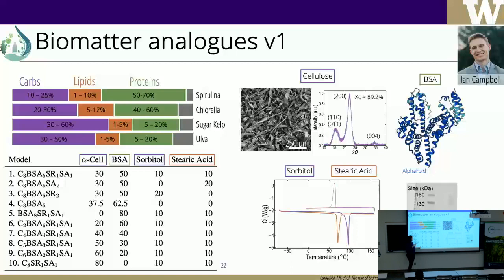So we chose alpha cellulose as our high molecular weight carbohydrate, even though we only have it in 3 of these examples, so we don't have it in spirulina. BSA is going to be the representative protein. It falls within the molecular weight range, about 56, 58 kilodalton, that we have in our natural protein, but that's as much of the similarity as we can have. Sorbitol and stearic acid are going to be our small molecular weight carbohydrate and our lipid equivalent. So now we try and mix all of those in concentrations that are going to be similar to what we would find in biomass.